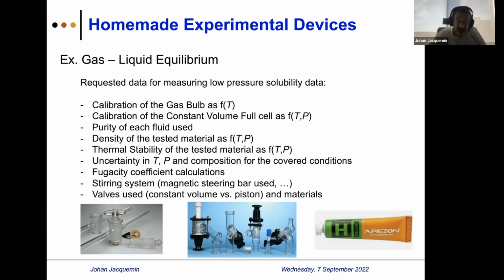And if you have to move to the glass valve, you must be aware that specifically Apiezon grease H, which is very well known for vacuum, could absorb a large quantity of hydrogen. I measured the solubility of hydrogen in Apiezon because I was starting to go crazy with data: the repetition of data was not there, and the calibration took ages, with a small decrease of pressure. And I discovered that the problem came from the valve. And the same for the stirring system, what type of bar you use. It's better to use glass, but the problem with glass in an isochoric technique is that if you break the glass, you have to recalibrate everything.